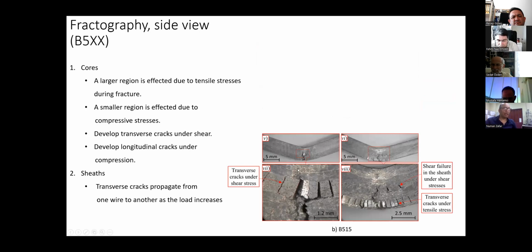Here you can see, I showed you the bottom plane, that the cores failed with the transverse cracks, but it can also be seen that in the middle layers the cores are also preferably failed with the transverse cracks. But in the sheaths, it does not happen. The sheath is more compliant to the type of stresses. If it is exposed to compressive stresses, it fails under compression, and if it is exposed to shear stresses, it will have this type of failure mode, which is typical of a shear stress failure.